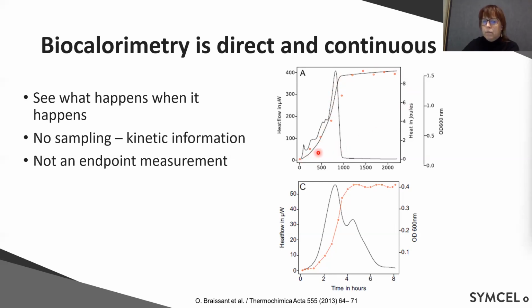We can see that the integrated values that I mentioned, the extent of the process, correlate quite well with the CFUs, with the OD increase here. So we can say that this correlates with that. But when we integrate the data, we lose a lot of information because there is a lot of things going on here. Could be used to identify your organism, or if you have other parallel measurements going on, you can see what is going on, which metabolites, what is it doing during this time.